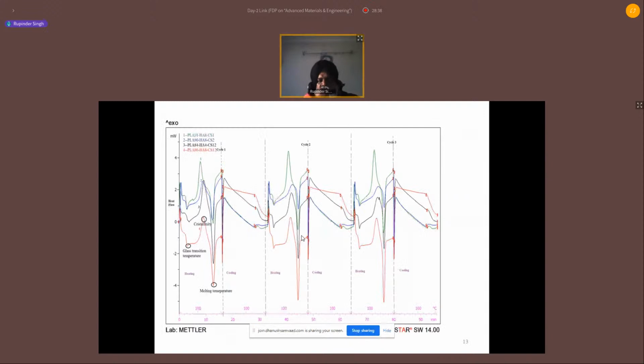This is again an important thing to understand. We tried to perform the thermal stability analysis of this particular material. You can see along the x-axis I am changing the temperature and the time, from room temperature to some high temperature, maybe around 150. Then again I am cooling from 150 to room temperature, then from room temperature to 150. So I am trying to see the energy absorbed in different heating and cooling cycles. I am interested in the crystallinity of the material, the glass transition temperature, and the melting temperature of this material.